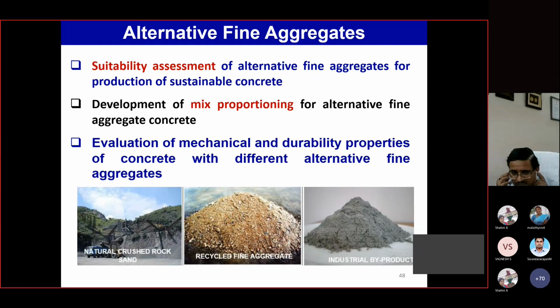We have worked on different types of alternative fine aggregates at CBRI, and we have developed and published methodology for that, looking into crushed rocks, recycled fine aggregate, coal bottom ash, and steel slag, that is called LD slag fine aggregate. We have done extensive studies on how we can use all those things. If you replace your natural fine aggregate with coal bottom ash by 30%, there is no problem, no loss in strength or other properties. The same happened with recycled fine aggregate. You can go up to 30% replacement of the natural.